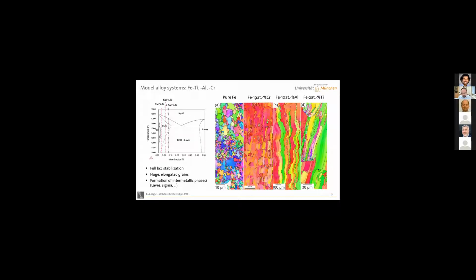Okay, so we work with a bunch of model alloys. I'm only showing some of them here. Later you will see a few more, but very simple alloys, iron plus X, to begin with. And we selected them for the nitride-forming ability on the one hand, but also for their ferrite stabilizing ability. In the beginning, we did that purely because we didn't want to deal with phase transformations on top of the gas interactions that we were looking at.